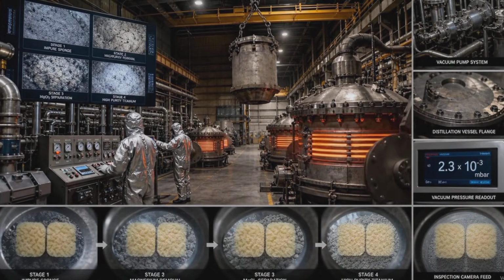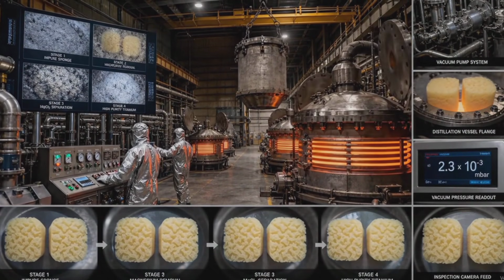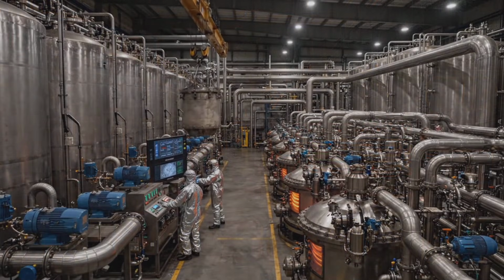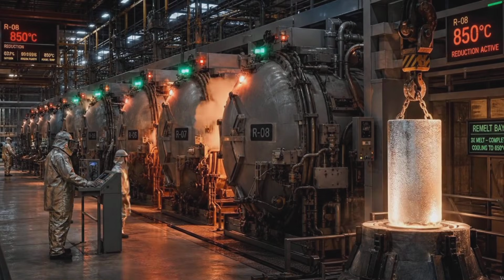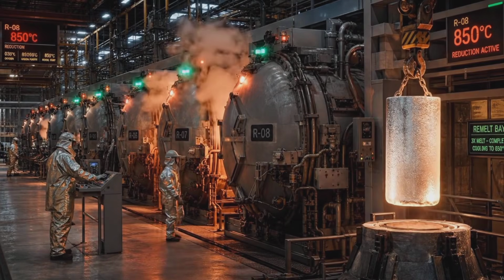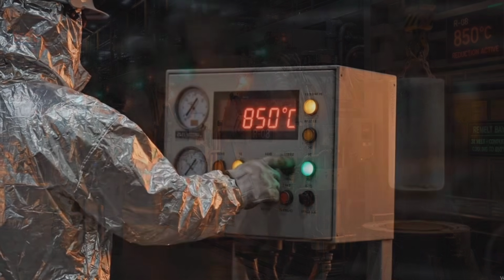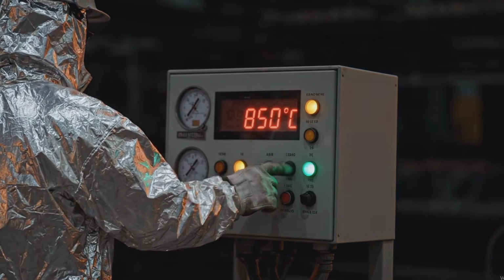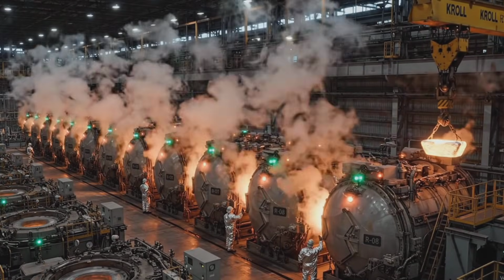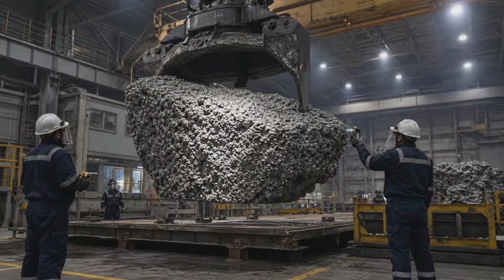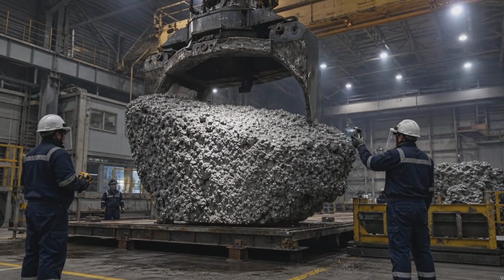Inside these reactors, in a sealed argon atmosphere, molten magnesium reacts with titanium tetrachloride. At 850 degrees Celsius, something extraordinary happens. Metallic titanium is born, a porous, gray, sponge-like mass known as titanium sponge. A journey that began with a simple rock has now reached the material that will conquer the sky.